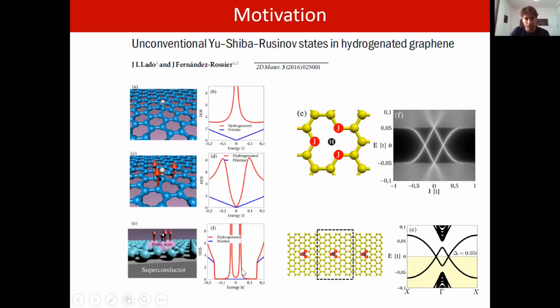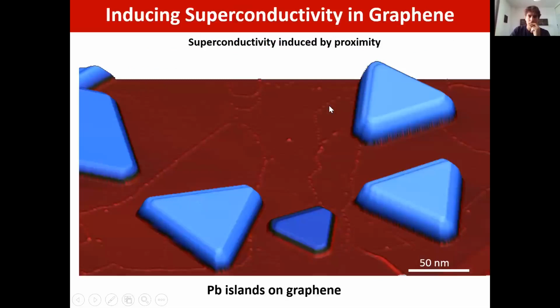You have in-gap states, which tells you that you have magnetic moments. And that's also very nice because they put a chain of hydrogen atoms, and they saw the interactions between those Yu-Shiba-Rusinov states, with the formation of Yu-Shiba-Rusinov bands. So you have most of the ingredients required to form Majorana states. Okay, so they were quick, and for us it took more time, because we have just published the paper now, so almost 5 years.